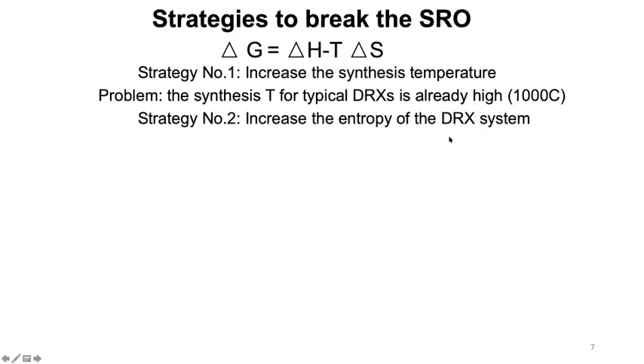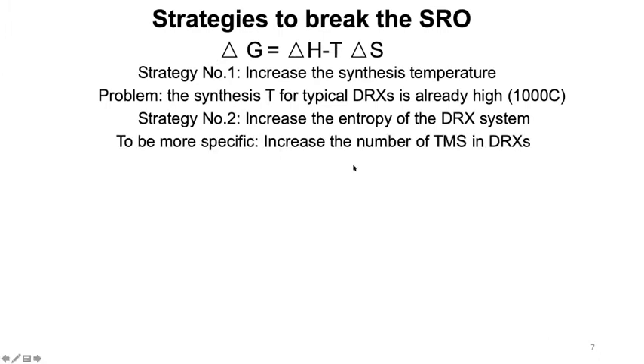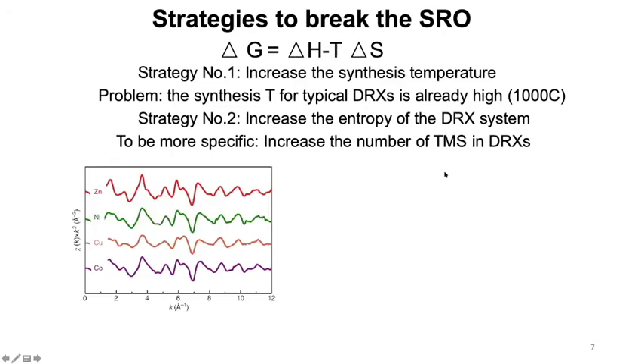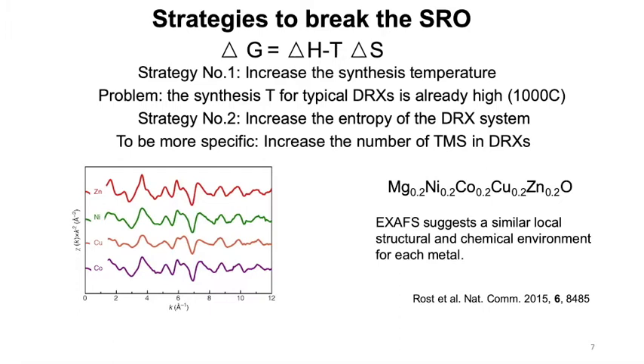And then the second strategy is if we can somehow increase the entropy term so that this product also becomes more negative, we can also decrease the overall Gibbs free energy change for this reaction. And we can also expect to reduce the short-range order. So that comes to the second strategy, that is to increase the number of transition metals in DRX so that we can benefit from the entropy effect. Actually, this strategy is promising because in some recent publications on high entropy oxide compounds, the EXAFS results suggest very similar local configuration for each transition metal, which means there is very little short-range order present in this high entropy oxide material.